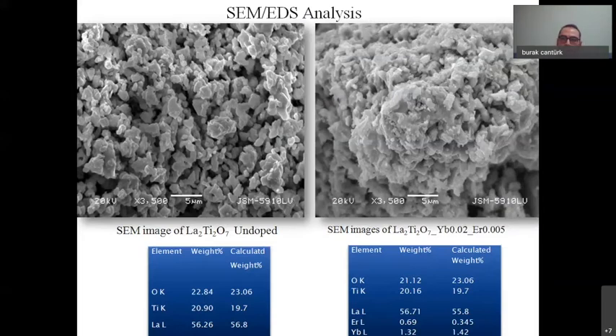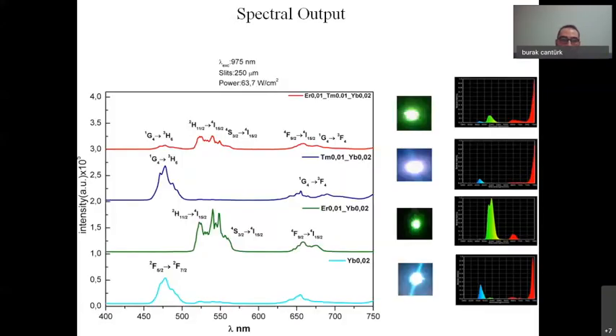Besides that, grain sizes were calculated via the Scherrer equation, and the result was, on average, 50 nanometers. You can see from the graphs that there are some spherical but mostly shapeless particle structures observed in here. Also, there's no big difference between the calculated weights and the outcomes, as we can see from the tables. And I think it can be deduced from some images that there is an agglomeration in this structure. Let's go to the next one.